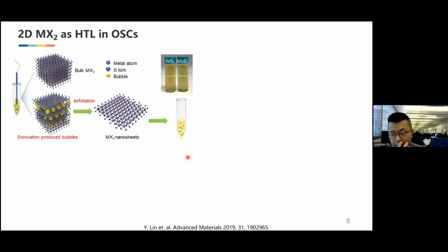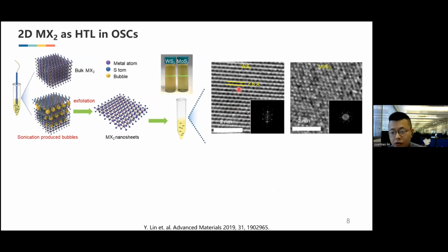So my first project was to use sonication to obtain 2D material nanosheets. We chose tungsten disulfide and molybdenum disulfide. From the high resolution TEM, the tungsten disulfide suspension nanosheets have a very clearly crystallized structure, but for the molybdenum disulfide, the structure is not obvious. This should be because of the multi-layer stacking of the MoS2 after the sonication.